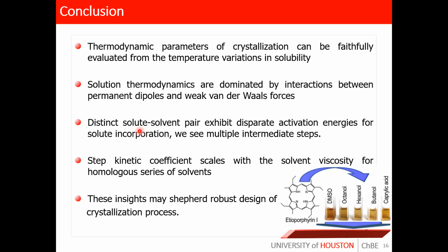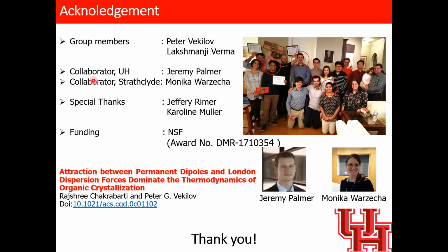We also show how different solute-solvent pairs will have different activation energy barriers for incorporation. And we show that for a homologous series of solvents, the alcohols, the step kinetic coefficient scales with the solvent viscosity. So understanding these insights into the molecular mechanisms of crystallization helps us design robust organic crystallization processes.